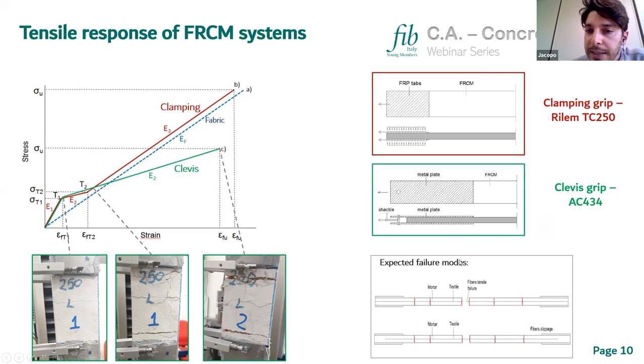So these are the expected failure modes. We can have the slippage of the fabric within the mortar, and this happens usually when we have low adhesion between the fiber and the mortar, but we can also have breakage of the fabric.